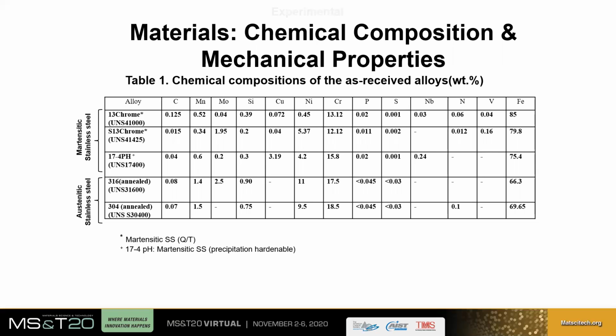17-4 PH has more than 15% chromium, along with nickel and copper, whereas 13 chrome and super 13 chrome have close to 13% chromium, and super 13 chrome has 2% molybdenum. We also used two austenitic stainless steel grades, 316 and 304. 316 has chromium close to 17%, but the nickel is higher in this case, and there is 2.5% moly in 316 grade, whereas 304 is free from moly.